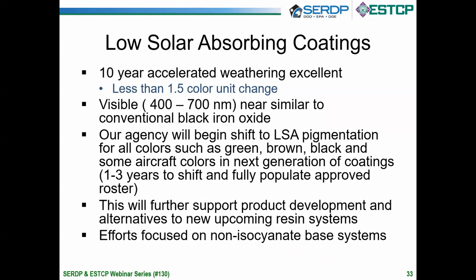In fact, using LSA pigments after a 10-year equivalent of accelerated weathering, we had less than 1.5 color unit change. Exceptional performance, proving the premise that LSA pigments could do what we needed to do for our systems. This was even achieved with our black CARC, which would be the most highly solar loading, and the pigmentation visually was very similar using the LSA.